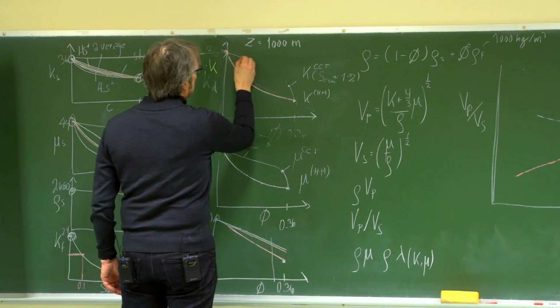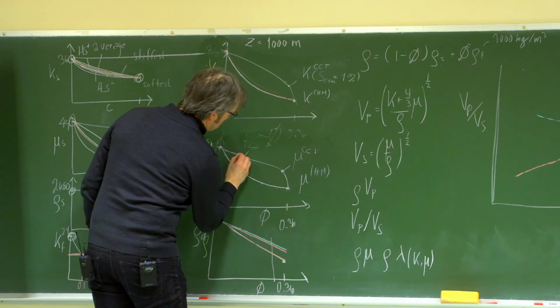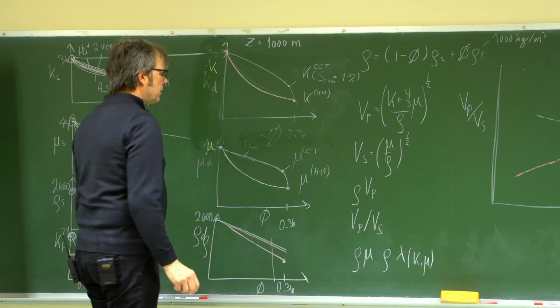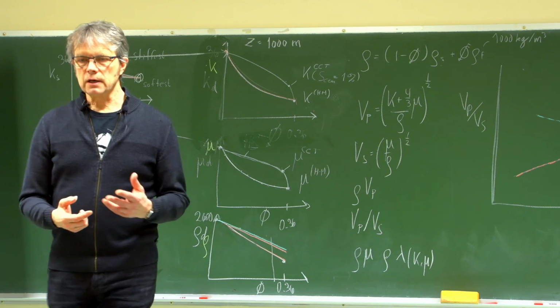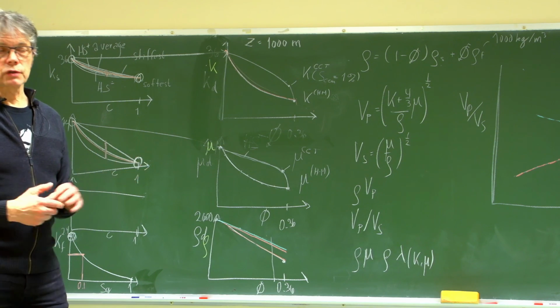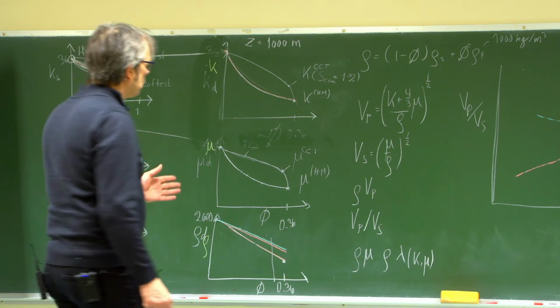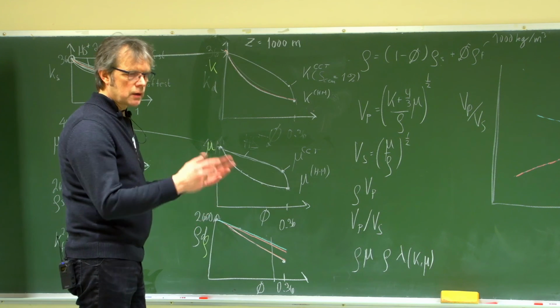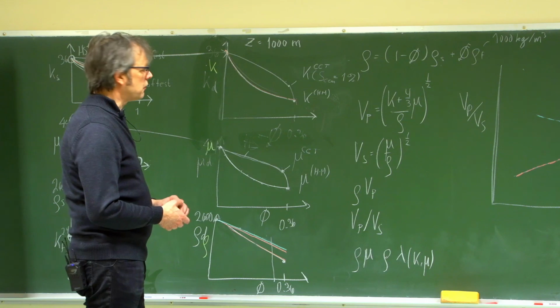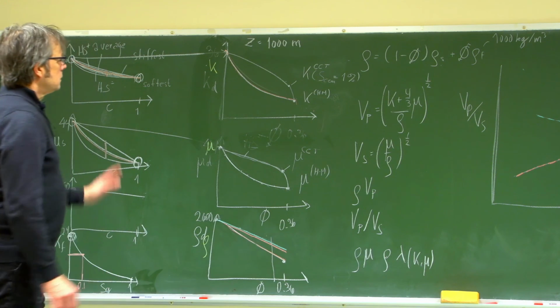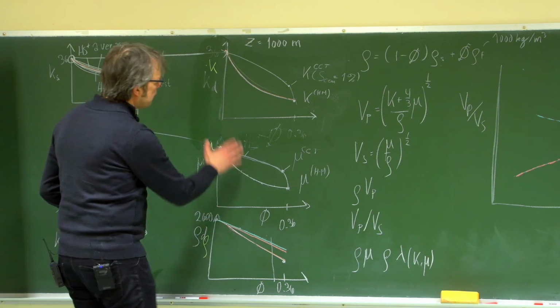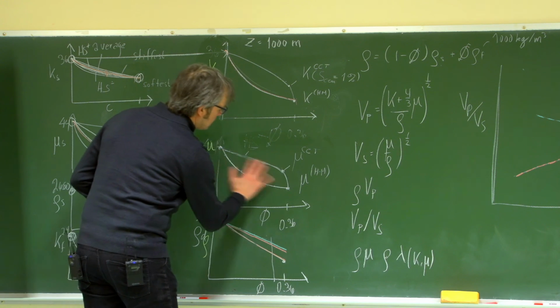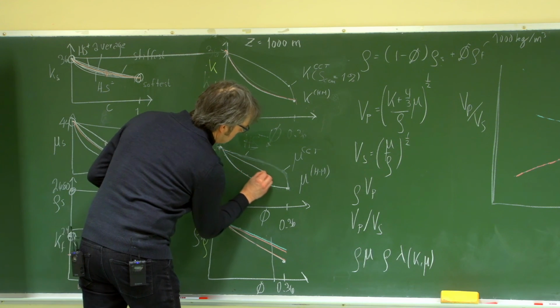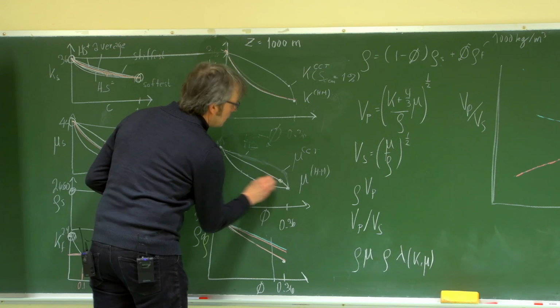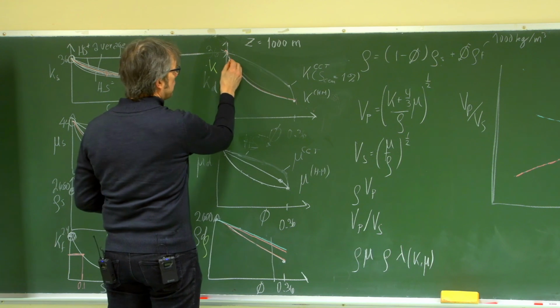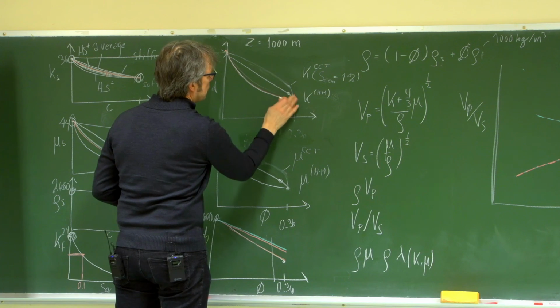And same here. So it should maybe go more like this. But you could, of course, argue if you are using a clay as a cementing material that you would like to use a lower Hertz-Mindlin bond, because you think that the clay is then becoming a phase that is surrounding some of the stiffer grains and so forth. So basically, this is the effect. Now I've exaggerated the effect here. It should, in fact, have been a bit smaller here. So it maybe should be down here. So the first percent is down here, same here, because otherwise I lose the fluid effect here. So something like this.